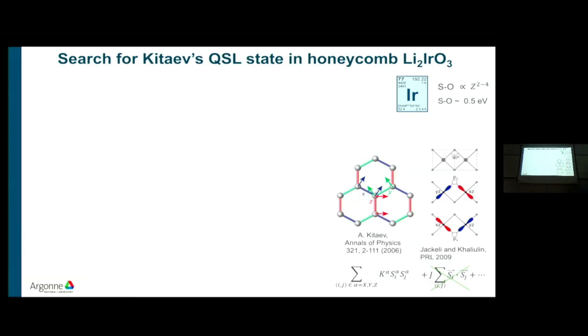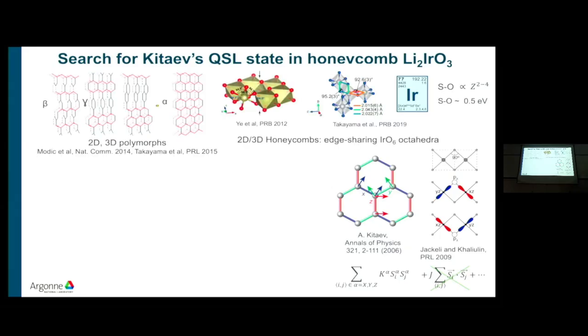This isotropic exchange only depends on the relative orientation of the spins. It doesn't care about the orientations relative to the lattice. So if this is cancelled and the Kitaev term survives, you can get a Kitaev spin liquid in a real material that has edge-shared octahedra with perfect 90-degree bonding. This system has different polymorphs, two-dimensional and three-dimensional. They are called 2D honeycombs, stripy and hyper honeycombs, but all of them have this motif of hexagons with corners with three bonds that could in principle host this predominant Kitaev interaction. But unfortunately, the angles in the structure are not 90 degrees, although they are edge-shared octahedra, and the distances are not all the same.